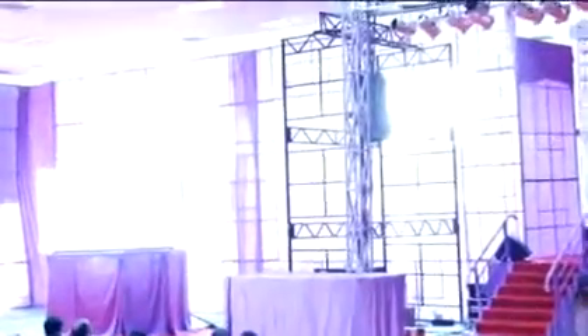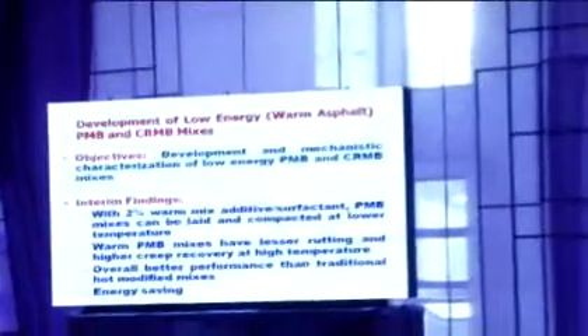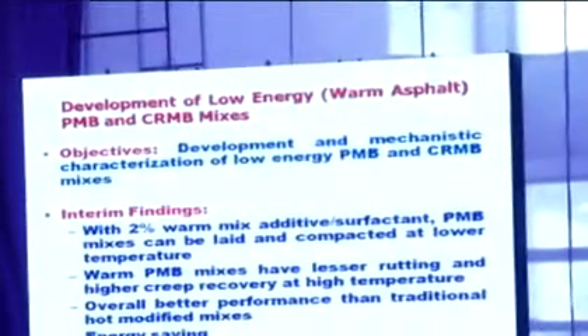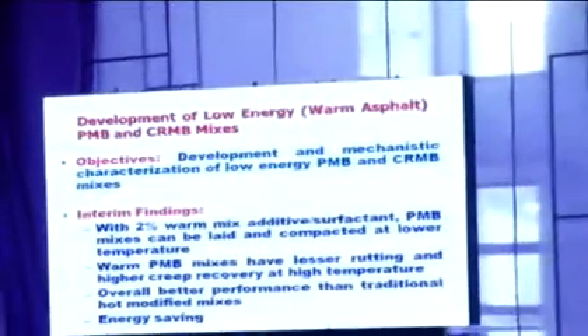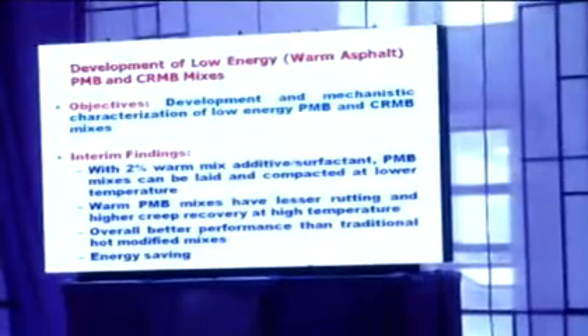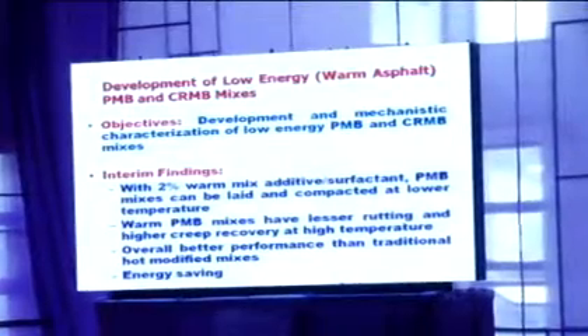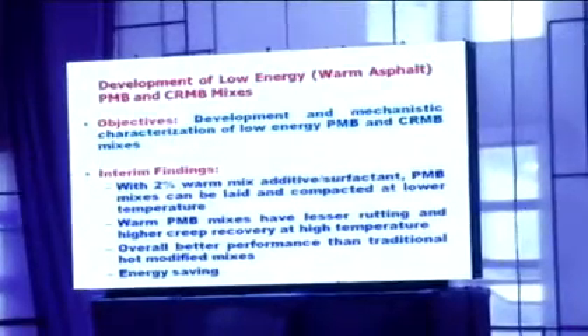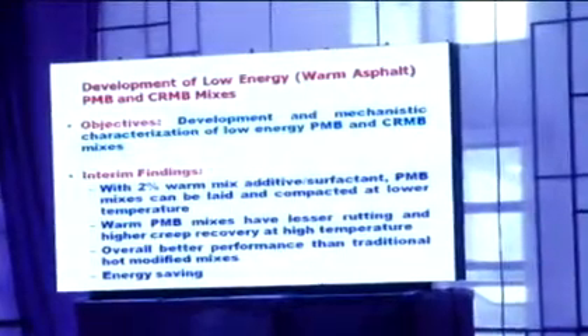First, flexible pavements. 7 numbers of projects have been reported for the first time, 9 are either ongoing or completed, and overall 16 projects have been reported this time in flexible pavements. First, development of low energy, that means warm asphalt, PMB and CRMB mixes. Objective is development and mechanistic characterization of low energy PMB and CRMB mixes. Interim findings reported are that with 2% warm mix additive, polymer modified bitumen mixes can be laid and compacted at lower temperature. Warm PMB mixes have lesser rutting and higher creep recovery at higher temperature. Overall better performance than traditional hot modified mixes and energy savings.